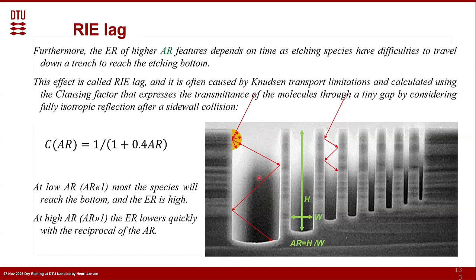And you can see that all the time it will knock at the wall. There's always a reasonable chance that it will go back. That means that the more times it will hit, the bigger the chance it will just be going back. And that's Knudsen transport. So it means that in high aspect ratio structures, relatively much fewer radicals will reach the bottom than for the big ones. And that's RIE lag. And it will follow roughly this formula. It depends, but roughly. So that's the basic idea. Smaller structures etch slower.